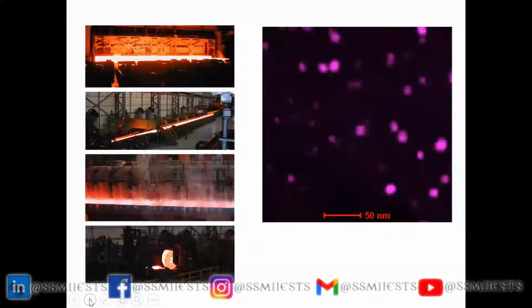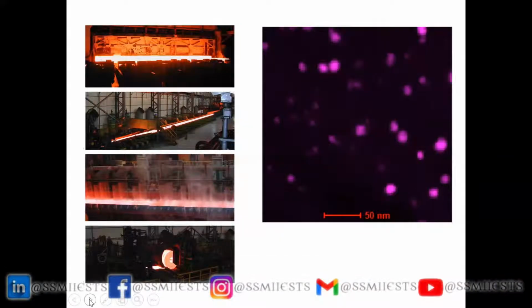we can microalloy the steel with vanadium carbides. Why with vanadium carbides rather than niobium carbides? Because we want a finish rolling temperature that is very low. Okay, and niobium carbides generally precipitate at a high temperature when you have a high carbon concentration. So here we are talking about 0.38% carbon, and niobium carbides would be lost before the finish rolling temperature. So what we want to do is we want to pancake the austenite grains so severely that the effective grain size becomes incredibly small. Okay, so if you go to the next slide,